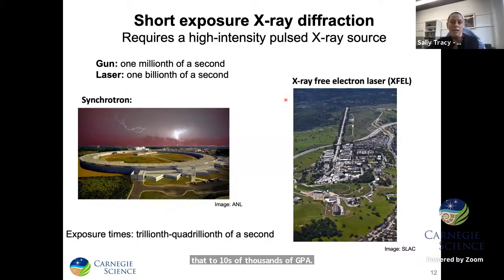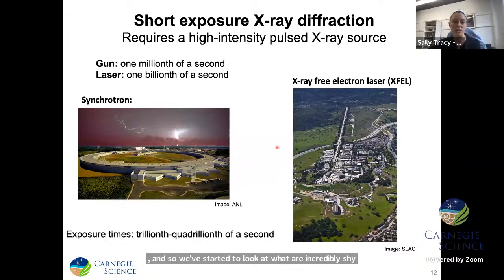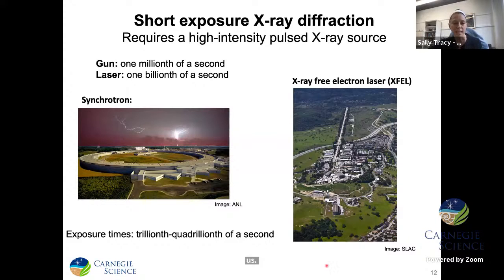The caveat, however, with this type of dynamic compression or shock loading experiment is that, as I mentioned, the high pressure state is really transient. And so we're starting to look at incredibly short loading durations. A typical gun-based experiment lasts on the order of a microsecond, or a millionth of a second, whereas these laser drive compression experiments are even shorter, typically a few nanoseconds, or a few billionths of a second. And so this presents a unique challenge of finding experimental probes that can collect high quality data with really high time resolutions on these ultra fast length scales.